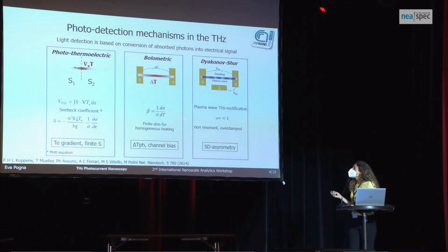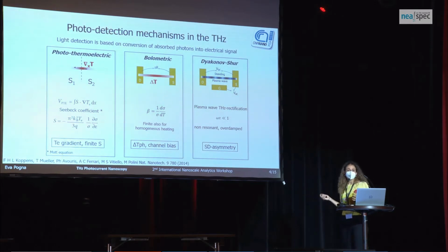Basically, the photodetection mechanisms that can come into play at terahertz frequencies are three: the thermally driven photothermoelectric effect, the bolometric effect, and the Dyakonov-Shur mechanism, which is the rectification of terahertz radiation by plasma waves, which in the non-resonant regime gives rise to a very broad response and relies on an asymmetry between the source and the drain contacts.